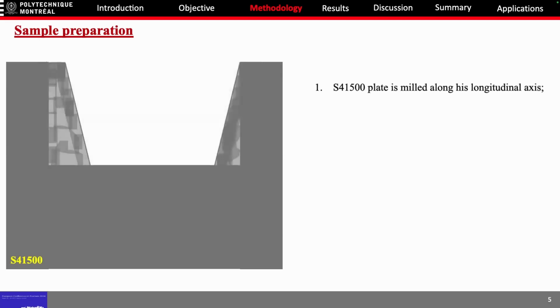So we needed to introduce artificial defects in a base metal to do the fatigue tests of some specimens. For the sample preparation, this is a plate of S41500, illustrated here. It is basically stainless steel, and we build a cavity along this longitudinal axis.